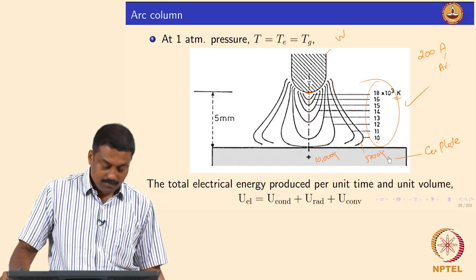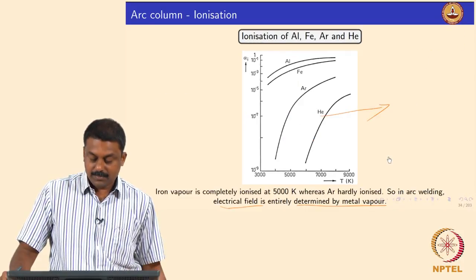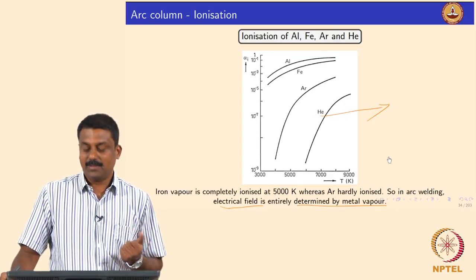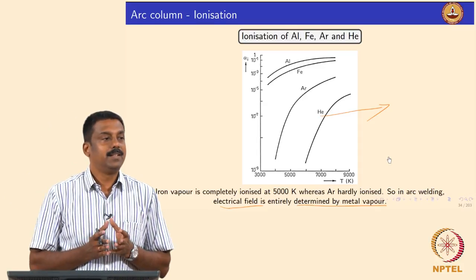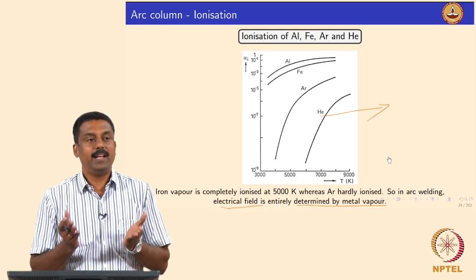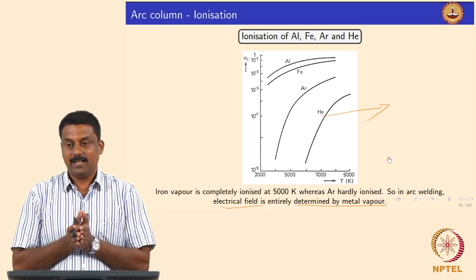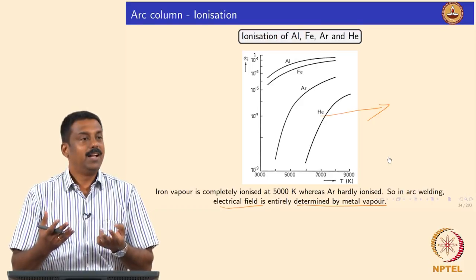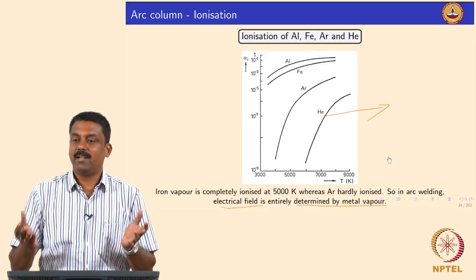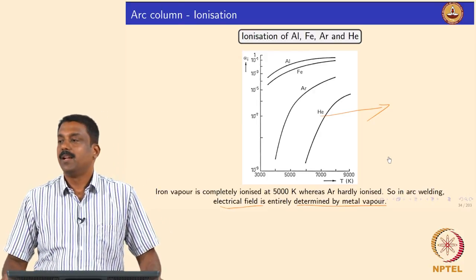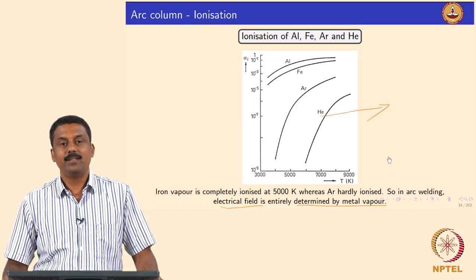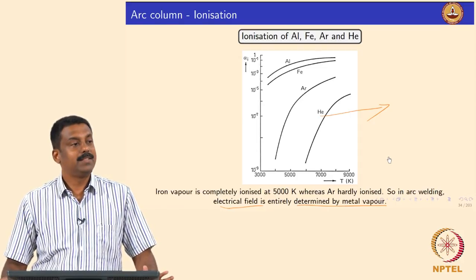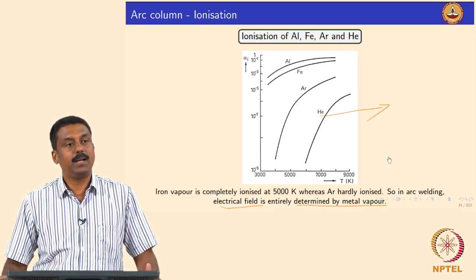Suppose if you start vaporizing the anode, the temperature would drastically come down. The arc column temperature will not be moving beyond 10,000 Kelvin and the envelope will be close to 5000 Kelvin in a real welding case where you are welding a metal or alloy — because in that case the metal vapor would determine your arc temperature. So the lesson here is: when you have gases with very high ionization energy, your arc temperature will also be high.